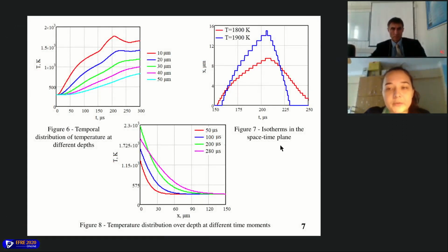Because we see satisfactory agreement before, we also wanted to show different ways of analyzing those thermophysical processes happening in the surface layer. So for example, in figure 6, you may see the temporal distribution of temperature at different depths. On figure 7, there are isotherms in the space-time plane. From that graph, you may find out information about, for example, with the red line, we may say that the surface of the target was heated to 1800 kelvins for 10 micrometers.